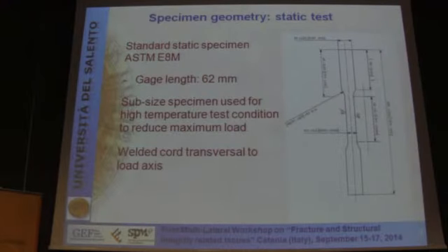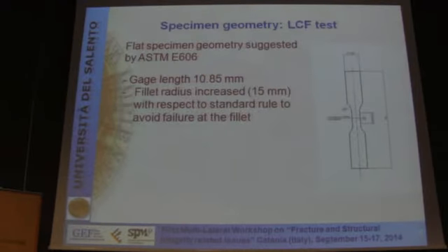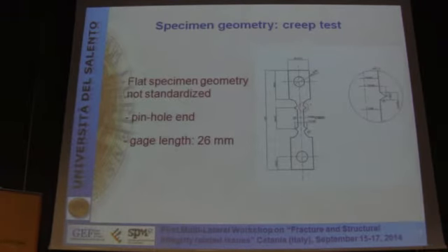This is the case of a static test, which uses the standard ASTM specimen. The weld bead is transversal to the load axis and is located in the mid-size of the specimen for all kinds of specimen. This is the LCF specimen. In this case, we used the recommendation of the ASTM rule, but we needed to increase the fillet radius because we observed several failures at the fillet. And finally, this is the creep test specimen for flat condition, which is not standardized.